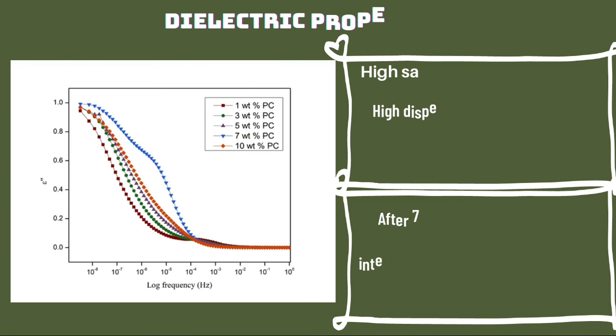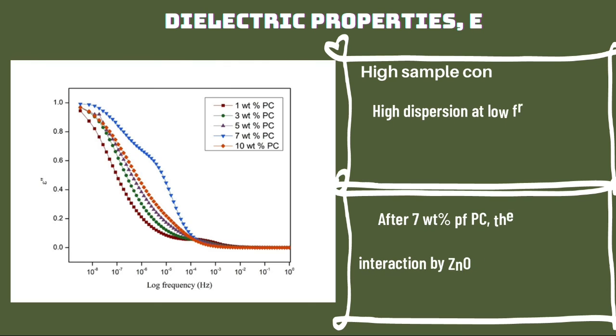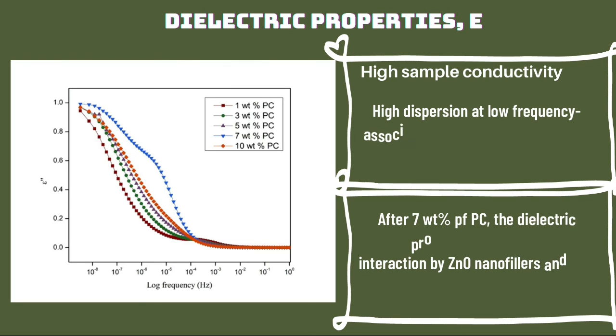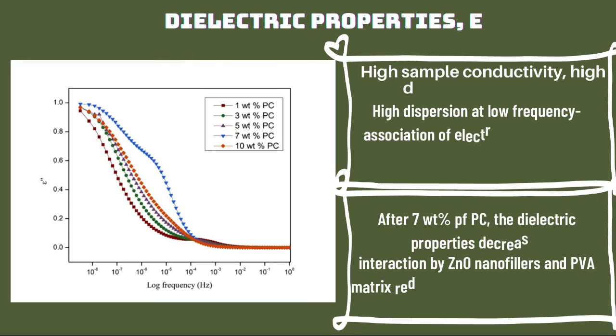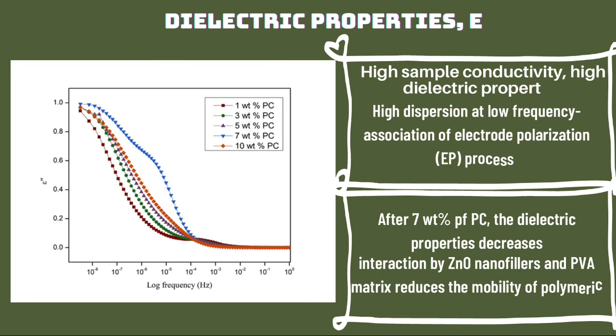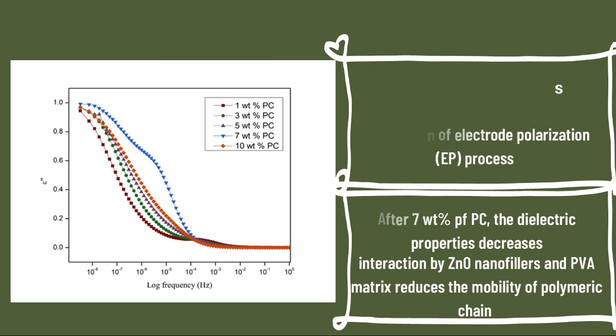Next, we proceed to the dielectric properties of the sample. This is a graph of dielectric constant versus log frequency. As we can see, high sample conductivity exhibits high dielectric properties. This is because of high dispersion at low frequency associated with the electrode polarization process. After 7 weight%, the dielectric properties decrease due to the interaction of zinc oxide nanoparticles with the PVA matrix.